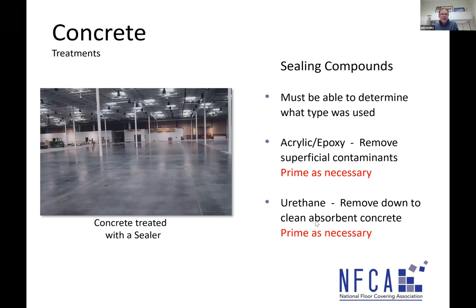Sealing compounds. Okay, there's acrylic sealers, epoxy sealers and coatings out there. And there are products out there that are able to stick to these surfaces, provided they're clean. Might be a two-component primer. Again, check with your manufacturers, and you have to be 100% certain with what product was used. Urethanes, on the other hand, are very difficult to adhere to. And there's other products out there like methyl methacrylates and polyaspartics that are also difficult to stick to. So again, get with your manufacturers. If we're certain that it's an acrylic, certain that it's an epoxy, you can do some test areas with the right primer and have success.